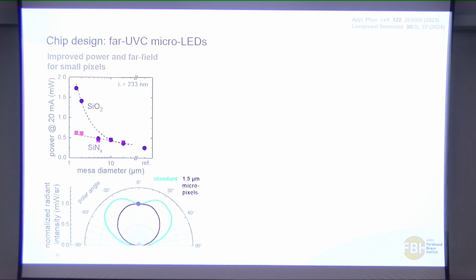And a very interesting effect of this is also that if you look at the far field of such LED chips, so typically if you didn't have these micropixels, you just had these large LED structures, then you would have such a form with these typical rabbit ears in the far field distribution. So actually the maximum in the intensity at the angle which light is emitted is not at 0 degrees, but at 30 degrees. But with these micropixels, we now have a more Lambertian pattern. So this is also very promising if you want to couple the light into a fiber for different applications. So this is one of the good side effects of this design.